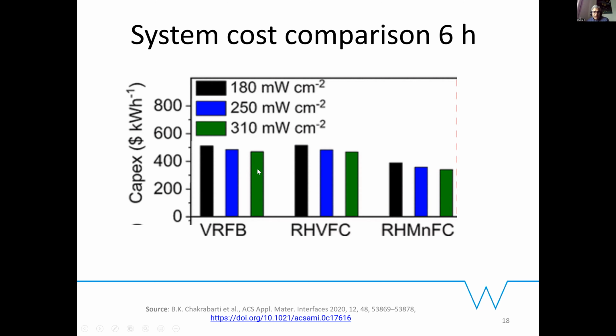However, if we replace one side of the vanadium with hydrogen, at higher current densities, the costing is slightly lower, even though it's not very clear, but still if you project a line from here, you'll see that the cost is lower at higher current densities. And obviously for the hydrogen manganese system, the costing is much lower because manganese is ubiquitous, it's a much cheaper material than vanadium, more available.